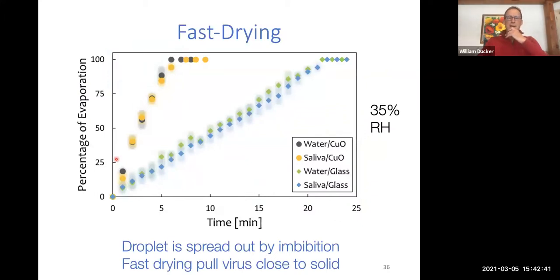I just want to point out, as my second to last slide, we did discover some interesting science on the way. It's not much use having a porous film if it just gets filled up with water and doesn't dry in between. So we looked at the effect of a porous film on how fast things dry. This is our control, where the droplet dried in about 20 minutes. And this is the porous film, and it dried about three or four times more quickly.